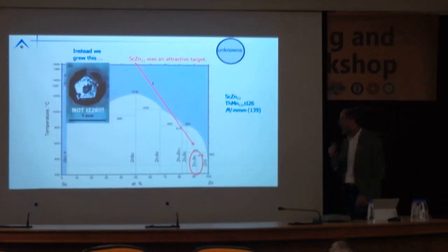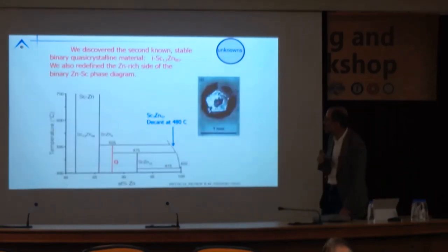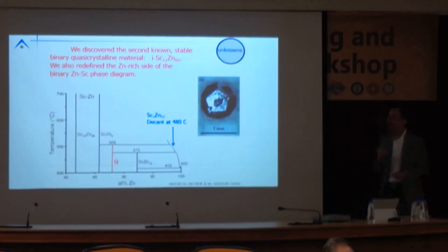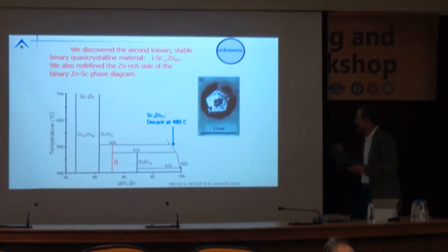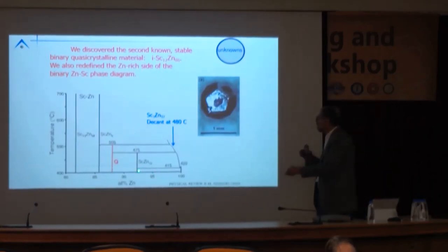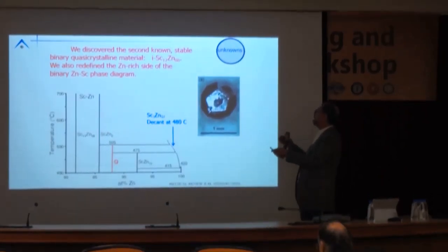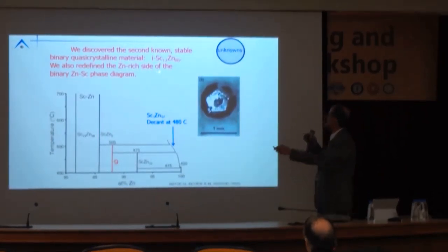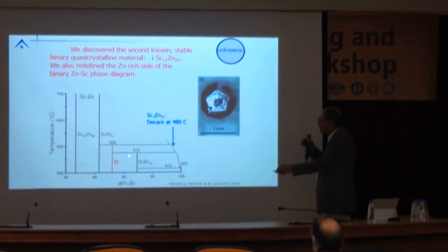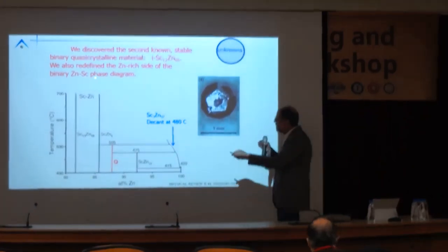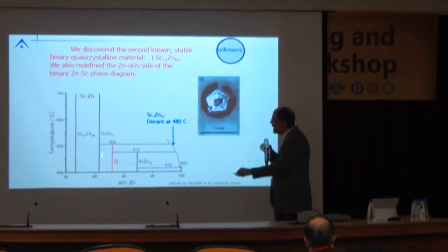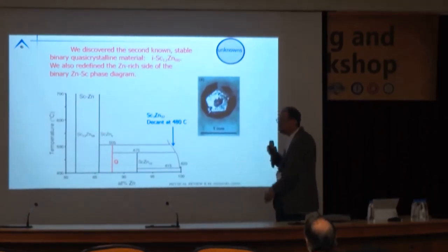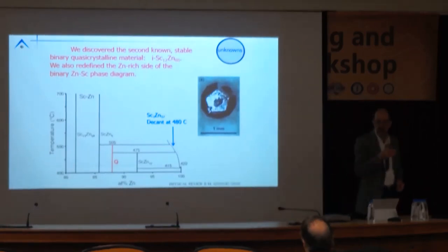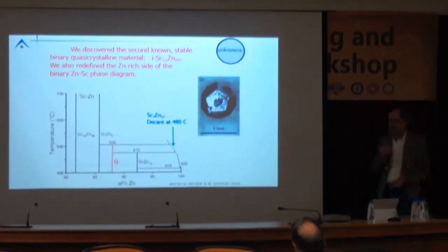Okay? So, what happened is we had to redefine the phase diagram. And you know, this is something we're doing more and more of these days, and I sort of take offense at it. It's not my job to make these types of phase diagrams. But on the other hand, we had to add another compound. Here's a quasicrystalline phase. This is the second known stable binary quasicrystal. Icosahedral scandium zinc, okay? And back to Pierce's question, we appreciated it's right next to scandium zinc 6, which is a crystalline approximant, okay? Cubic or tetragonal.